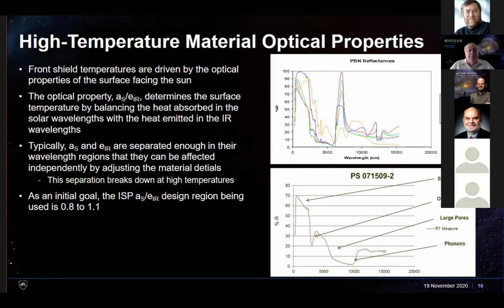If I have this coating and I put it into an oven and heat it up to whatever temperature I'm going to, it will have a new reflectance profile when it comes down. What's happening is that the porosity at the small end changes and the material relaxes. My pores expand out, my grains grow and things like that, so I have a different reflective structure. My absorbance goes down in the low wavelength, and when my absorbance goes down, my temperature goes up.